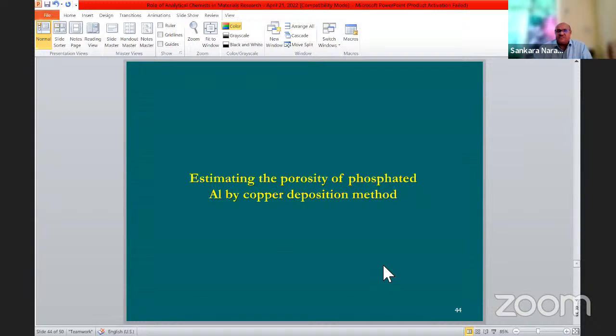Okay, that leads to the formation of a Prussian blue color. So the same reaction is exposed. When there is porosity in a phosphated steel compound, you can take a potassium ferricyanide solution, immerse a filter paper in the potassium ferricyanide solution and apply it over the phosphated steel. What will happen is the uncoated area, the bare steel, will be exposed.